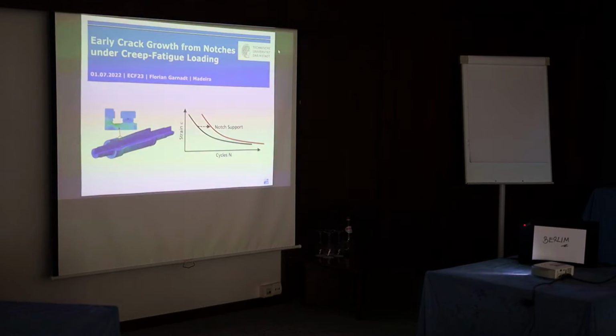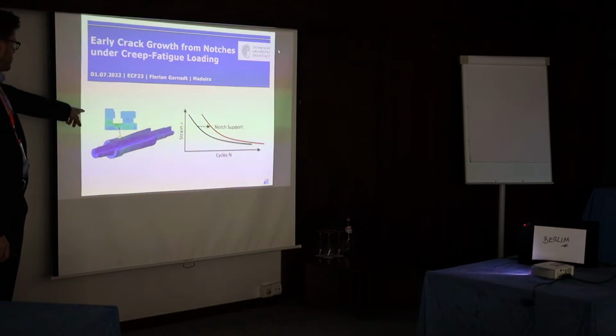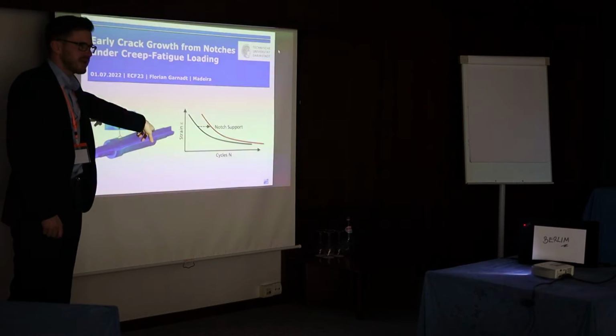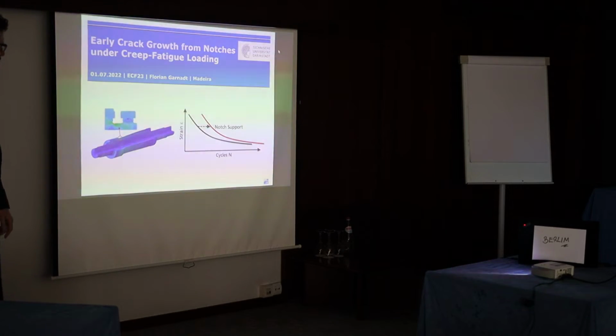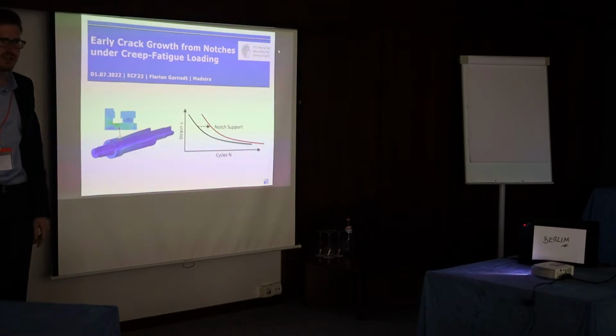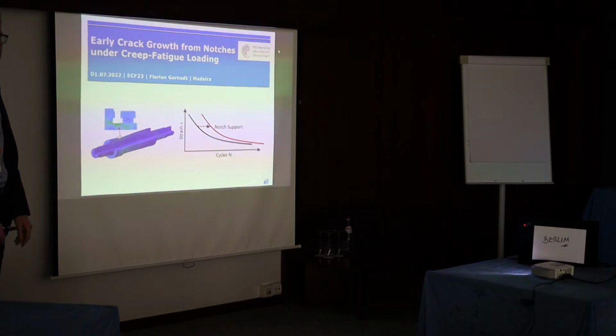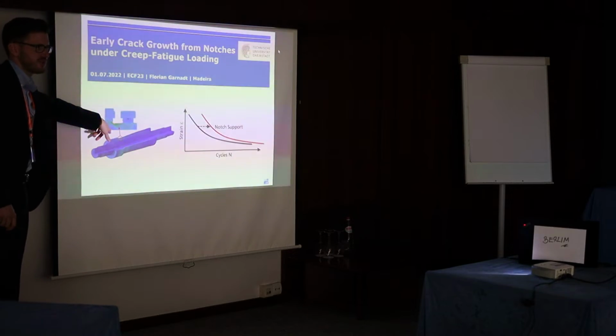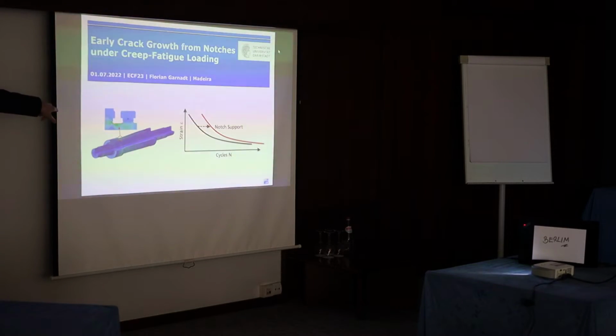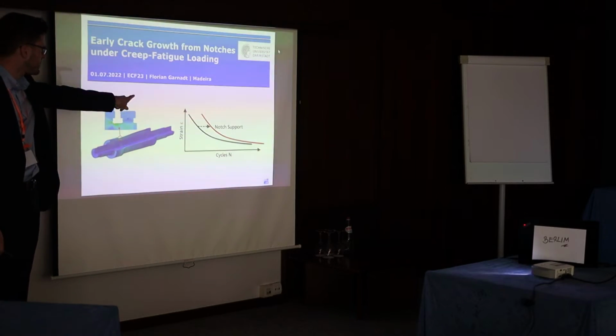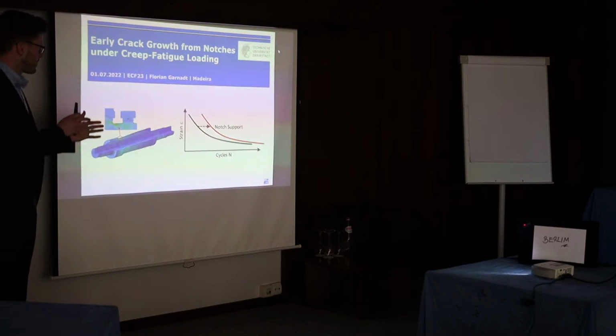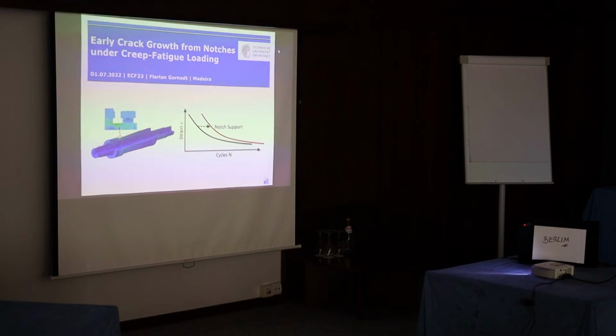What is then done in your lifetime assessment is you determine your local loading and go into a fatigue life curve, like you can see here on the right, this black curve, and determine your number of cycles to crack initiation. But what is completely neglected here is the effect of notch support, which comes from the stress gradient, which you obviously have here. And if you consider this in your determination of the number of cycles for crack initiation, you end up with this red curve. So this lifetime beneficial effect, in my opinion, needs to be considered here.